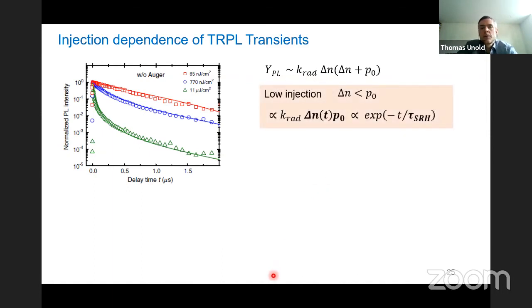Now you have to distinguish importantly between two conditions. One is low injection, when your delta N is smaller than the P zero. That's the case either if the doping is high or you have very, very low excitation conditions. In order to reach them, you need a very sensitive setup. And then if you have Shockley-Read-Hall recombination, then basically you'll have a mono exponential here with the lifetime as the exponent.